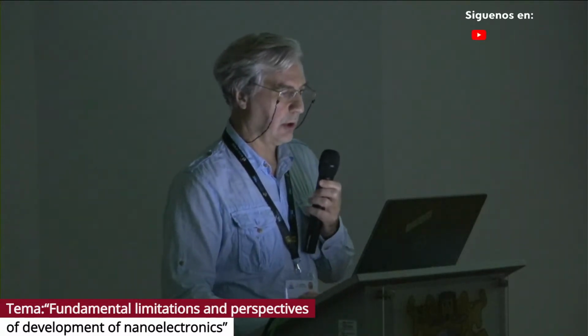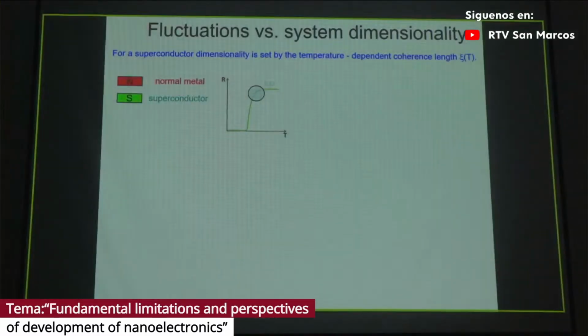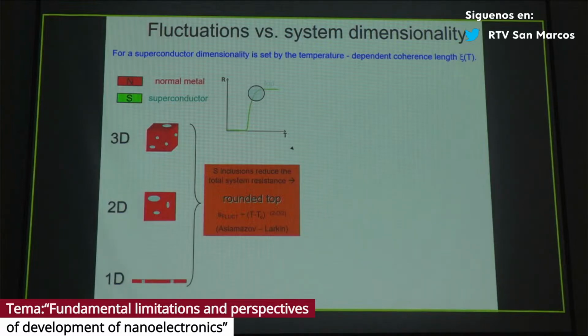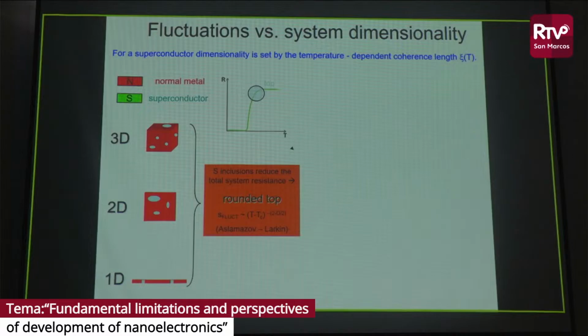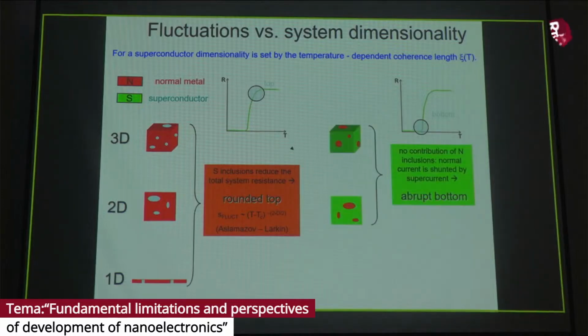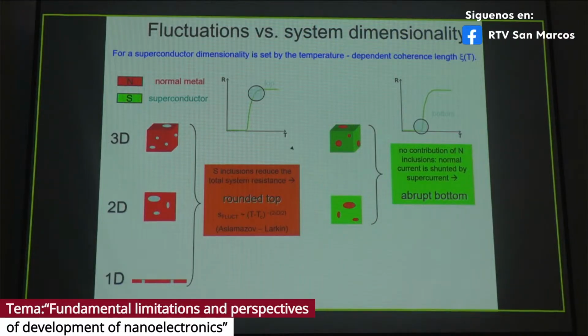On this small cartoon, everything which is in a normal state I will plot in red, everything which is superconducting will be green. If we speak about the top of the resistive transition, where the system is mainly in the normal state, the answer is very well known. It's the so-called Aslamazov-Larkin correction to electric conductivity, and that was nicely discussed in one of yesterday's talks. But what about when the system is mainly in the superconducting state, when here and there fluctuations create normal domains? One need not be an expert in superconductivity; just basic electrotechnical considerations are enough to understand that nothing interesting will happen. Electric current will always follow the green path, just avoiding going into red spots where the resistance is finite.